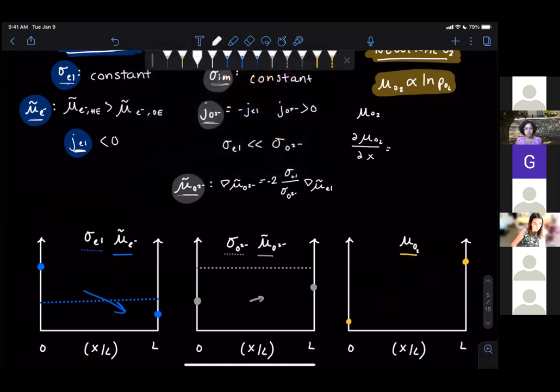But again, coming full circle, checking our work here, we know that the chemical potential of oxygen, based on the fact that this is a reaction that can equilibrate, is going to equal 2 times the electrochemical potential of the oxygen anion minus 4 times the electrochemical potential of the electron.